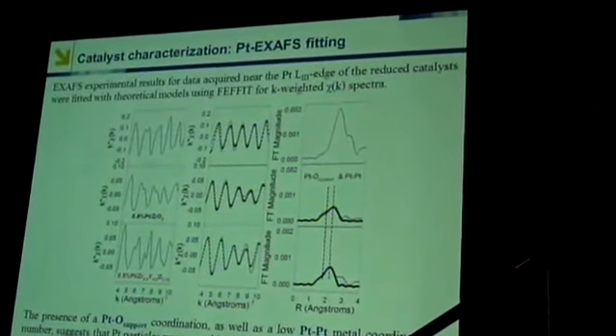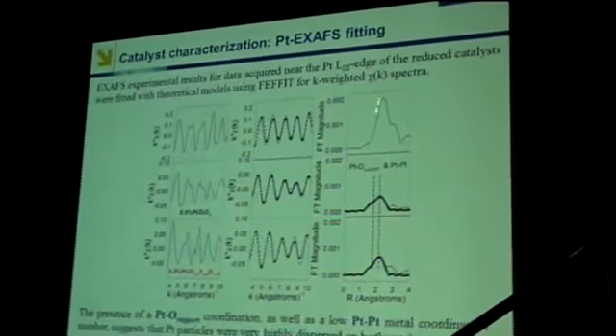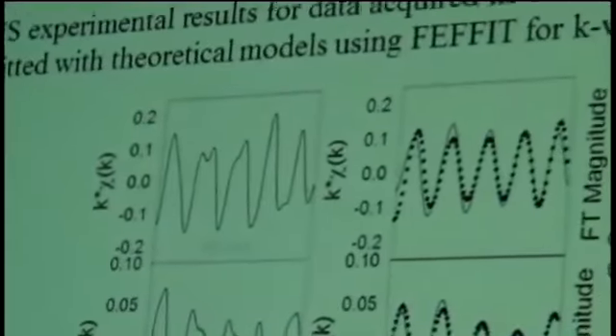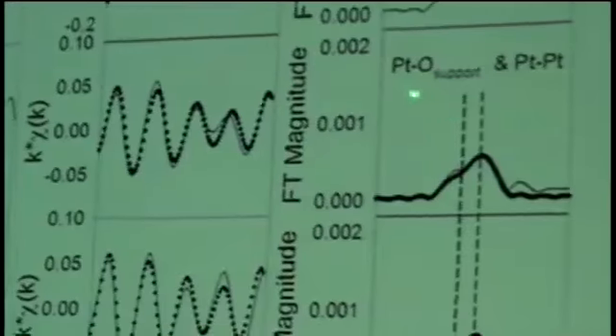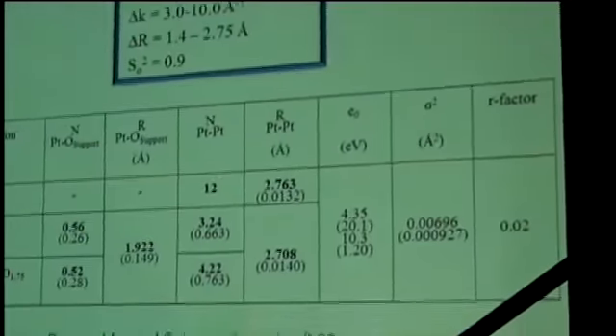When we cool the catalyst down and look at the XAS data, we can see that we have very, very small peaks for platinum coordination, indicating, again, small crystallites, small domains. And this would be the platinum foil with coordination number 12. We also had to include in the fitting a small platinum-oxygen support coordination as well. And so we were able to obtain reasonably good fittings, and we had very low platinum coordination, around 3 to 4, for these catalysts.